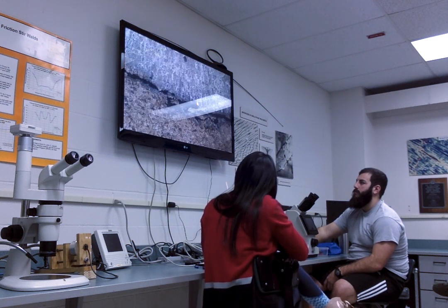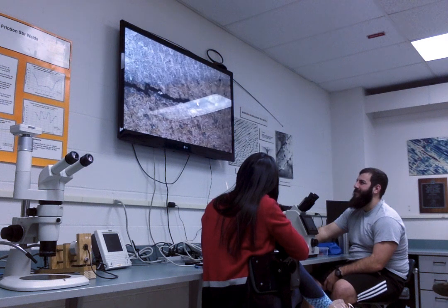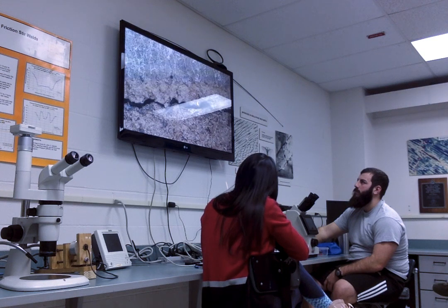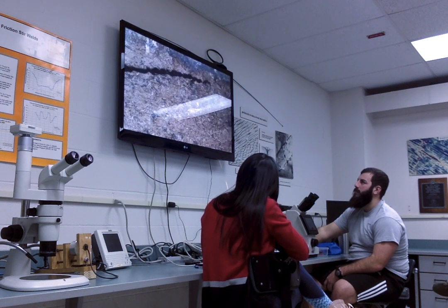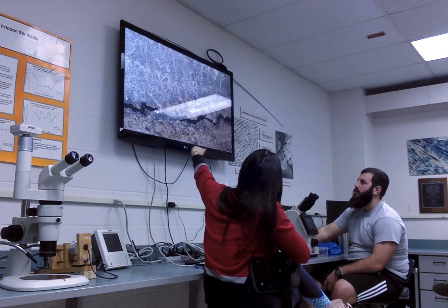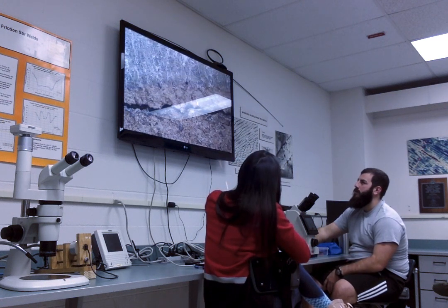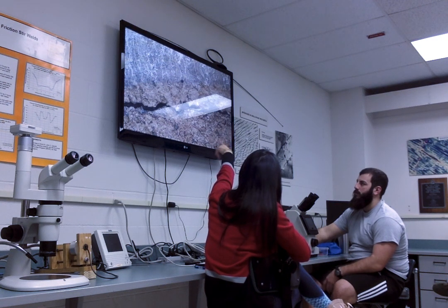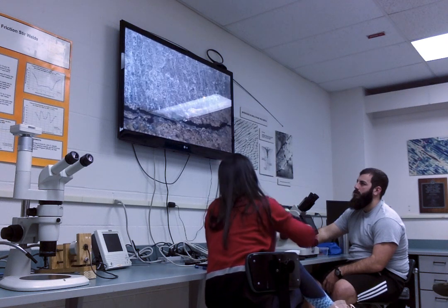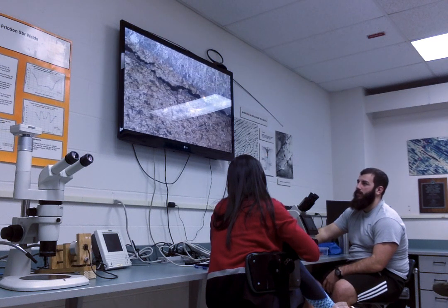So it's mostly intergranular, but there is a spot that might be transgranular over on the other side. That looks pretty straight, like on the bottom. Right there. Since it ended there, it probably propagated from the other side. So if we go to the beginning of it, that might be intergranular right there. See how it looks less straight, more jagged edges.